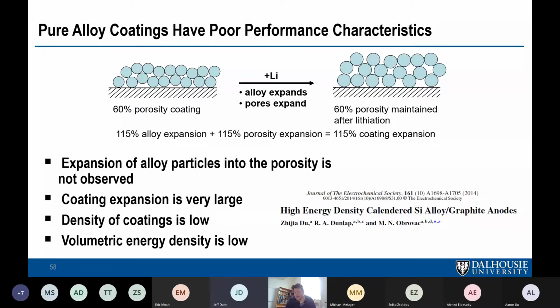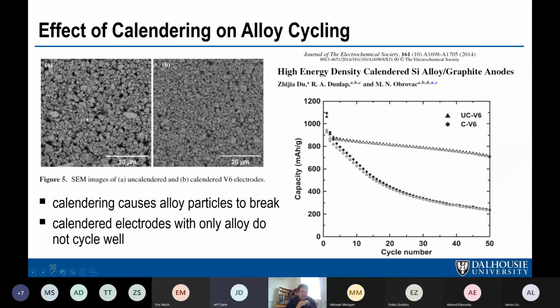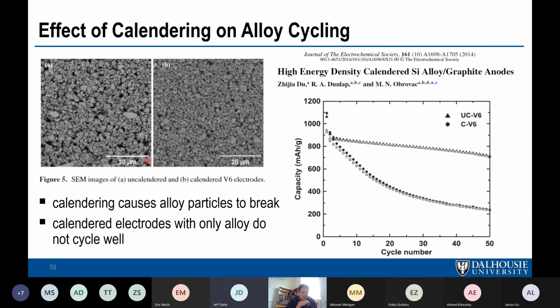Unless you have particles, maybe graphite flakes might be able to do that, but I don't know. In our experience, you can see that this distribution is huge on the left, right? This is a huge particle distribution. This is about as bimodal as you can get, and this is 60% porosity. In our experience, we've never been able to achieve high density without calendaring. I see. Okay, thank you.